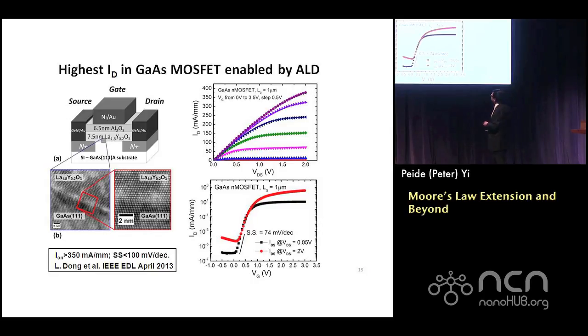So my group always identifies itself as researching ALD, and we cooperate with the Harvard group of Roy Gordon, as a chemist. Eventually we could grow even beyond that. We can not only grow the amorphous oxide, we can even grow epitaxial single crystal oxide on top of the gallium arsenide, just like MBE, but we grow at much lower temperature. The fundamental is ALD chemistry reactions, so you can have a very high quality interface on the gallium arsenide.